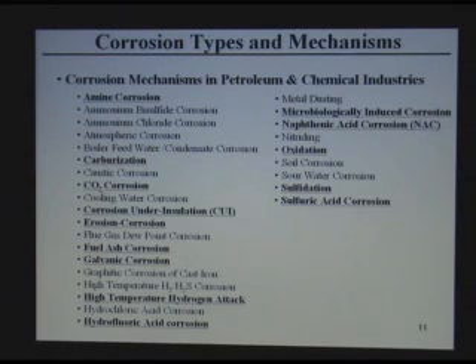Flue gas dew point corrosion: if you are burning in a heater fuel gas or oil which has a lot of sulfur, it produces SO2 in the gas, and then this SO2 forms sulfuric acid, and it condenses in the tail end of the furnace, in the cold end, and causes corrosion in the convection section of the furnace. Fuel ash corrosion: if you have vanadium or sodium in fuel oil that you burn in the heater, this ash deposits on the heater tubes and causes damage to the tubes.